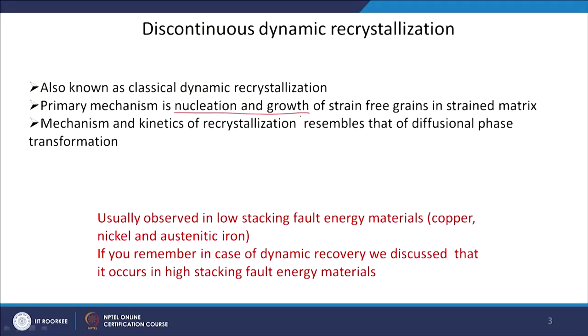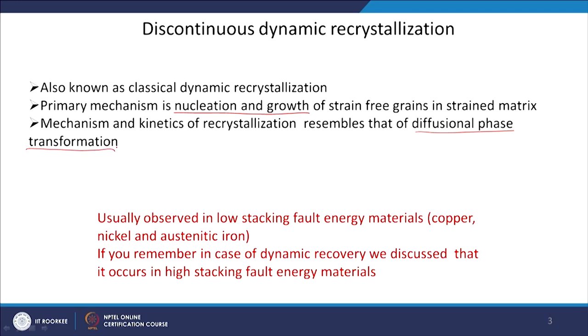What the material will try to do is nucleate a new strain-free grain within this strained matrix, which will grow until the whole matrix is covered by relatively strain-free new grains. This is what recrystallization is — formation of new strain-free grains in the strained grains. It is not a phase transformation; the same phase gets a new set of grains. The primary mechanism is nucleation and growth, and you can compare this with diffusional phase transformation, where similar kinetics and behaviour are observed.